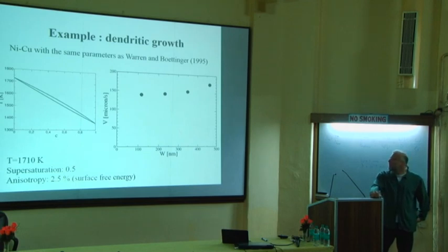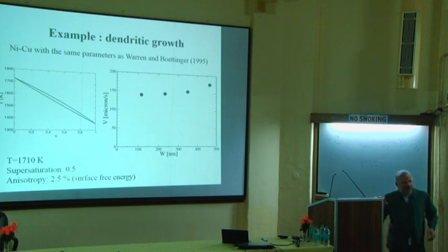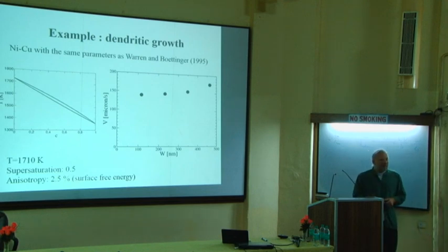I didn't give you the detail, but much asymptotic expansions. Expansion means a power series expansion. So you expand in the powers of this interface thickness, and then you equate order by order. So what often is called a quantitative phase field model is a model where you have eliminated all the linear errors. Okay. Then logically what you should see first as an error is the quadratic one. So I would generically expect, if you do such convergence curves, that you should see a quadratic dependence.